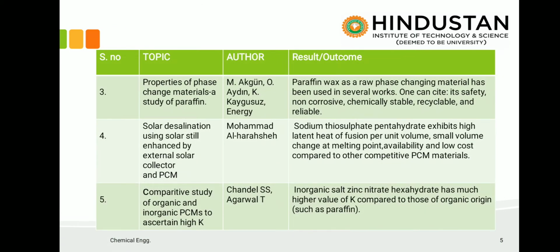Here, the properties of phase change materials, a study of paraffin. The study found paraffin to be safe, non-corrosive and chemically stable. These features of paraffin wax made me choose it as one of the three nano PCMs. And in solar desalination, sodium thiosulfate pentahydrate portrayed high latent heat of fusion per unit volume. This is the prime reason why I went for sodium thiosulfate pentahydrate. It exhibited a paramount amount of latent heat of fusion.